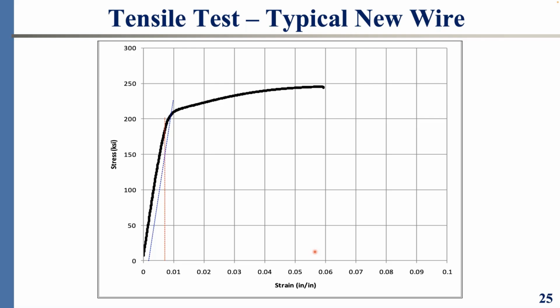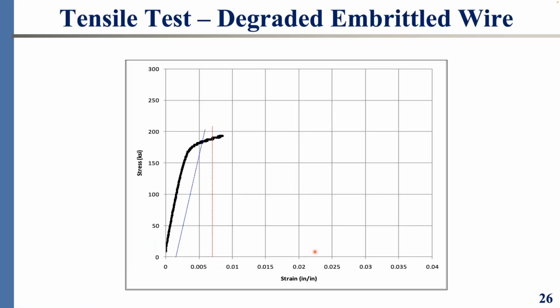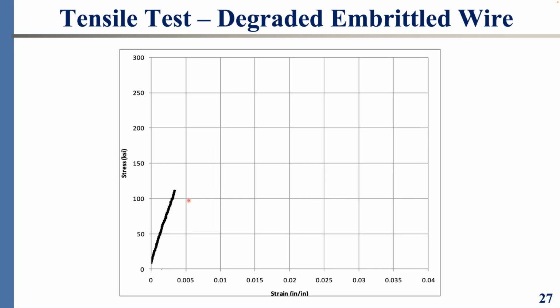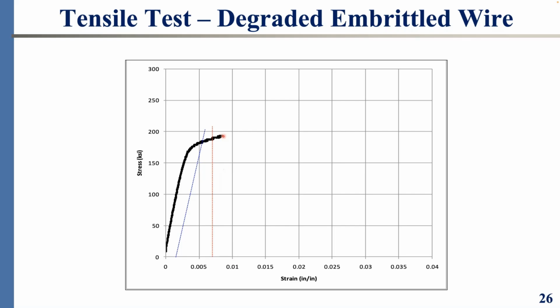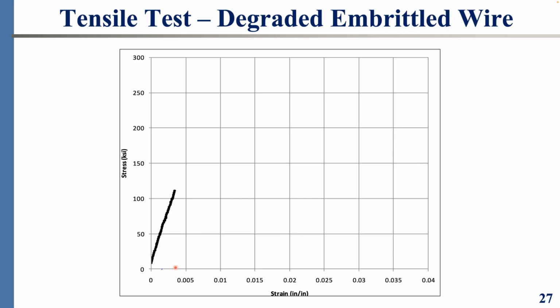But moving forward here, with the wire degradation, you start seeing reduction in ductility. Over here, for instance, it becomes less than 1%. Oh, wow. This is about a little below 0.8%. And over here, how about this? About 0.3% or a little over 0.3%. So these wires were taken out of the bridge cable. They were alive and well and carrying load. Case in point, the evidence of that is they survived the stress strain, the tensile test, up until a certain point, and then they snapped and broke. That is vivid demonstration of the embrittlement. And if you start looking at these three graphs, you find reduction in ductility. That's an order of magnitude between this value and this value, for instance, or even lower for some sampled wires.